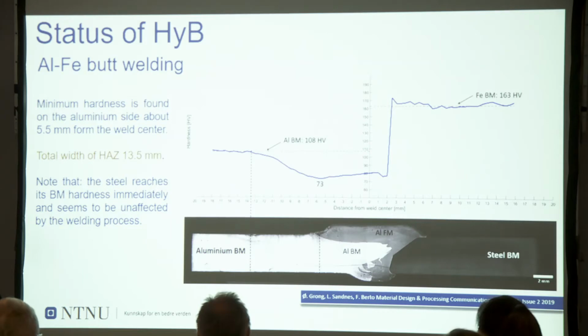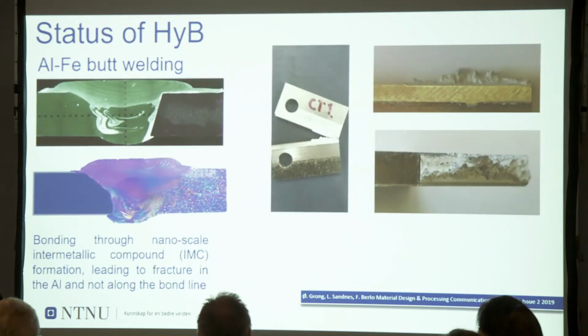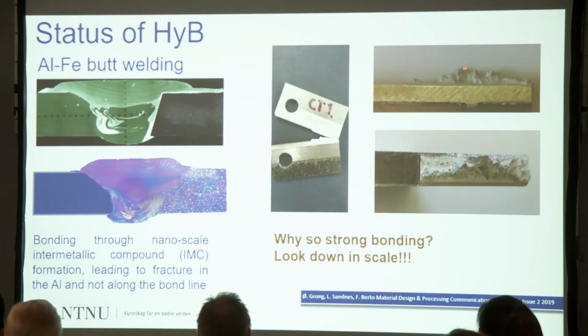The heat affected zone, or the zone that is affected by the welding, is also very limited, and this is a strong advantage for residual stress, that after that reflects also in very good fatigue properties, as I will show you later. Another important aspect is that the HyB bond, at least under static condition, was found to be a very strong bonding. In fact, the failure is not happening at the bonding interface, but is mainly failing in the aluminum part. So the bonding resists under the static loading condition. And why such a strong bonding has been found, I will explain later going down in scale.